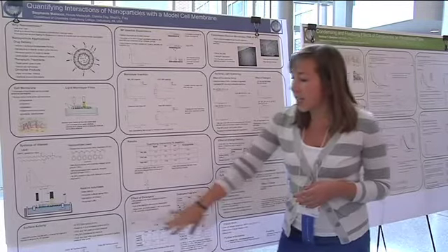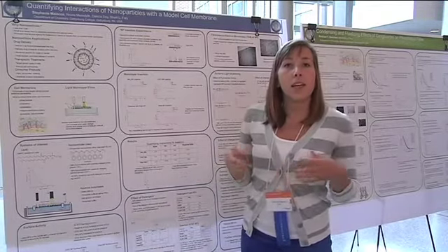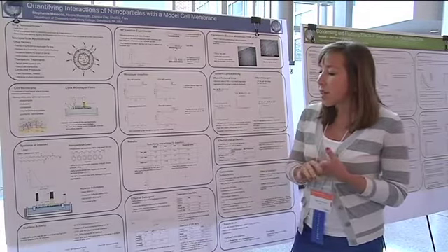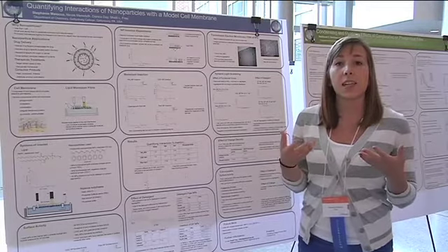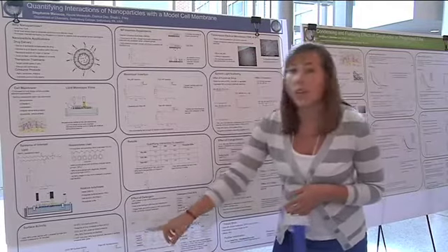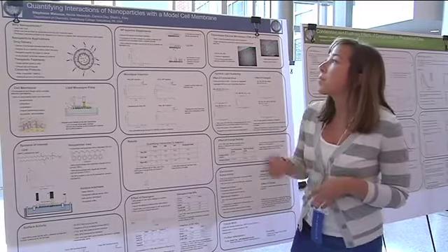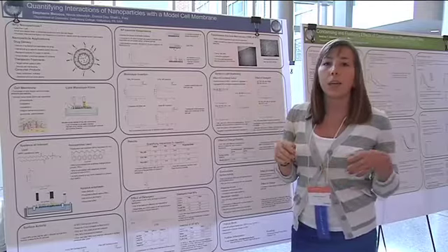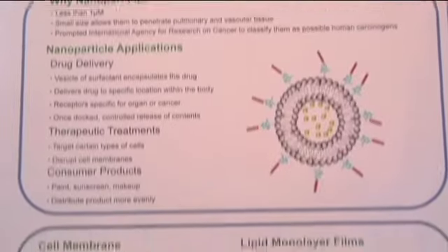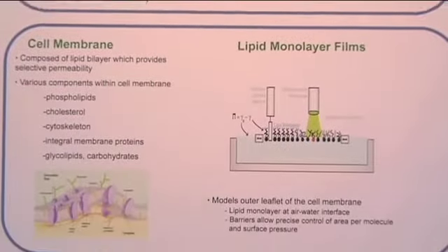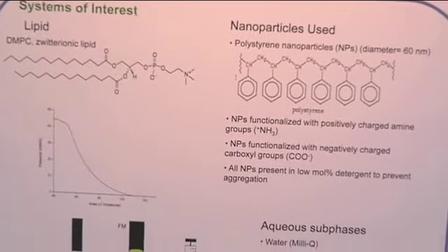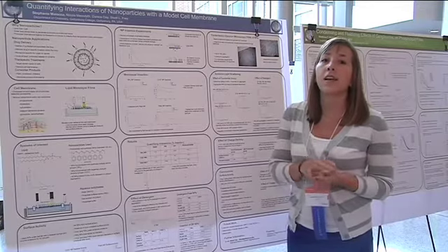So we've looked at the surface activity, to see when you inject them into a trough with no lipids at the interface, whether they have surface activity and come to the interface. So we've seen that all of the nanoparticles have surface activity. So for our insertion experiments, we inject the nanoparticles into the subphase, and the barriers will expand to allow the nanoparticles to come to the interface, if there's a strong driving force for them to be at the interface.